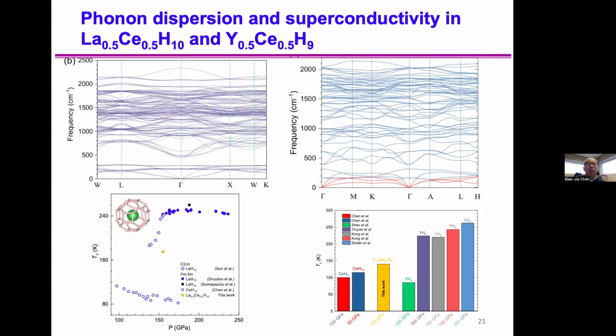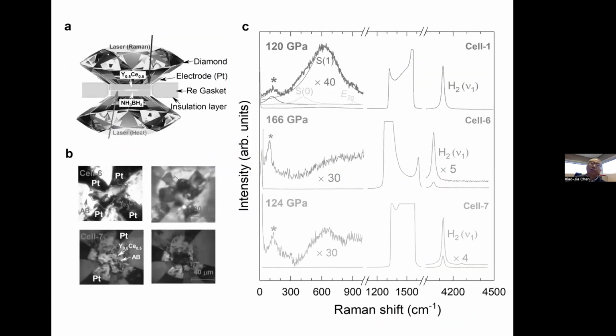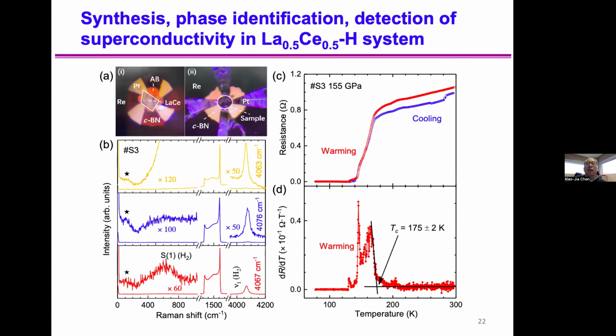Our Raman low frequency mode comes from the hydrides, based on the calculation. You can see at the top we have two calculations of the phonon dispersion at the gamma point, around 200 wave number in both compounds. That is the feature we observed here. Here I show you the lanthanum cerium 0.5 to 0.5 ratio hydrides, figure B. We mark a star. All these stars indicate the sample is already created. That's a fingerprint for hydrides besides hydrogen.